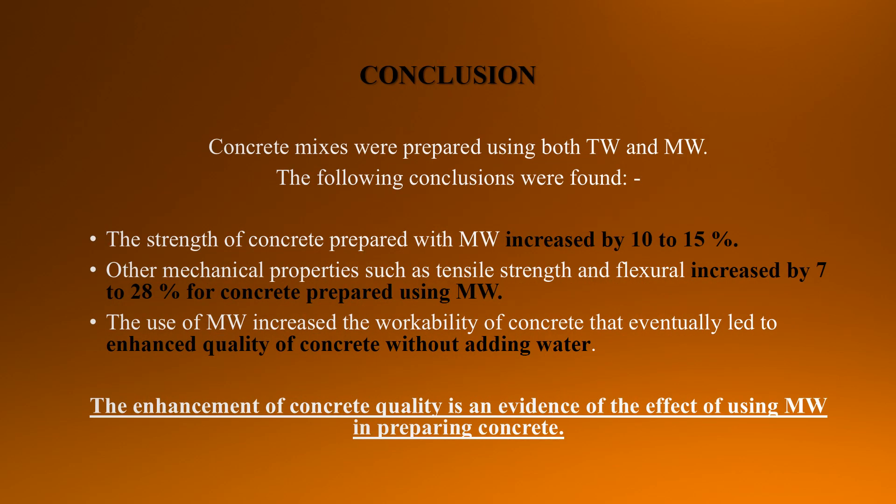Coming to the conclusion. Concrete mixtures were prepared using both tap water and magnetized water. The following conclusions were found: the strength of concrete prepared with magnetized water increased by 10 to 15%; other mechanical properties such as tensile strength and flexural strength increased by 7 to 28% for concrete prepared using magnetized water; and the use of magnetized water increased the workability of concrete, which eventually led to enhanced quality of concrete without adding water. The enhancement of concrete quality is an evidence of the effect of using magnetized water in preparing concrete.